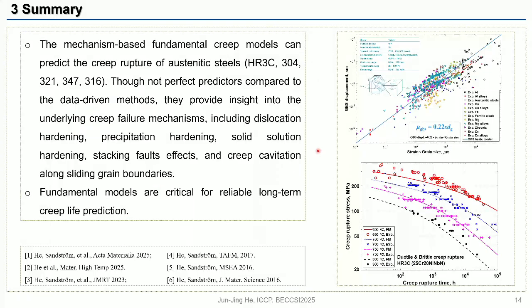In summary, the mechanism-based fundamental creep models can predict the creep rupture of austenitic steels. We have just shown one example for Sanicro 25 steels. It can also be applied to 304, 321, 347, and 316. Compared to the data-driven methods, they may not be perfect predictors, but they provide insight into the underlying creep failure mechanisms, including the dislocation, precipitation, solid solution hardening, stacking fault effect, and the creep cavitation along sliding grain boundaries. So they are critical for reliable long-term creep life prediction.